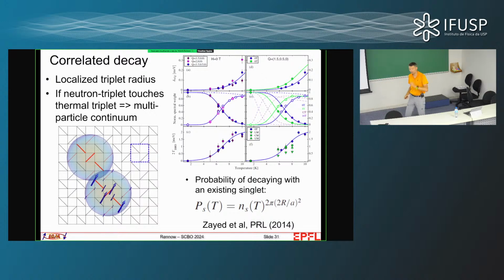So now I come with my neutron, I create another triplet, and there are two possibilities. Either the new triplet I created is far away from any of these thermally excited triplets, and if that happens, it has a long lifetime, so it contributes to the sharp peak, or it will overlap with a thermally excited triplet, in which case it will decay fast. Okay? Once I know the size, the radius of this thing, and the size of the gap for the thermal activation, I can predict the ratio of fast decay to slow decay. Basically that's this crossover here: the long lifetime component, as I increase the temperature, goes down, and the short lifetime component goes up.